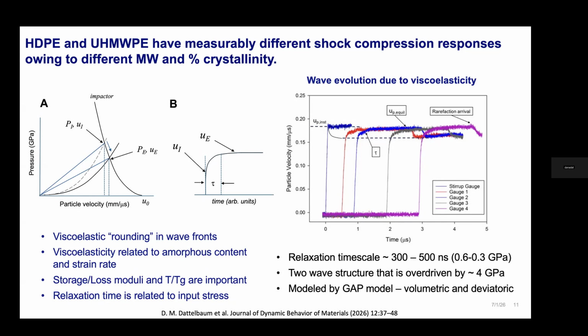The way we've been modeling this at LANL is that we have developed something called a GAP model, or a glassy amorphous polymer model, that Brad Clements developed. And with that model, again, I pointed this out earlier, he has both a volumetric, or essentially EOS, term, but also a deviatoric term in order to capture that. And he captures that through a Prony series expansion of Maxwell elements, which is a common approach for viscoelastic materials.